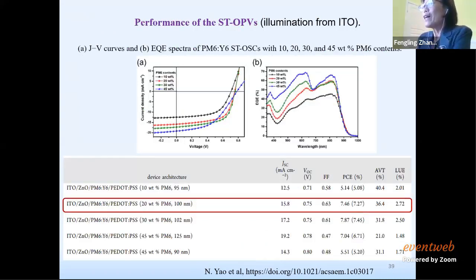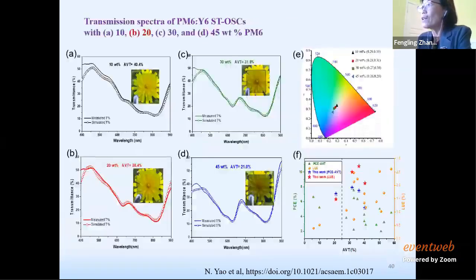So we make different devices with different stoichiometry to optimize the transmittance and also the power conversion efficiency. Here I highlight the 20% donor. For the 20% donor, we get the largest LUE, 2.7. Compared with the semi-transparent devices published so far, this number is quite good. It's among the high ones. Here I also show the photos. You can see from the photo, for the 20% red one, figure B, they balance the transparency and also the efficiency.